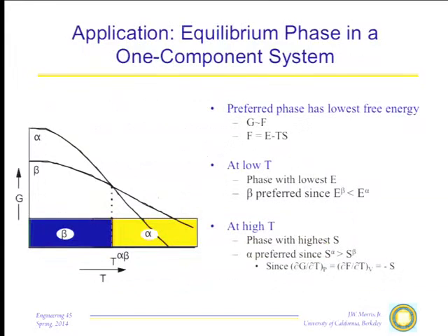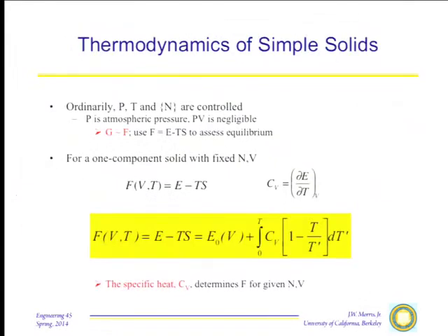We discussed the sources of the specific heat last time, and finished up last time. The specific heat of virtually all solids of interest to us is dominated by the vibrational contribution. And that has kind of a universal function. It goes like T cubed at low temperature and then asymptotes to a high temperature limit at a material parameter that's known as the Debye temperature. What the Debye temperature is, qualitatively, is just a temperature above which you can assume that all the vibrations are as activated as they can be. So if we know the Debye temperature, we have a pretty good idea of what the specific heat is, we can then calculate the Helmholtz free energy.